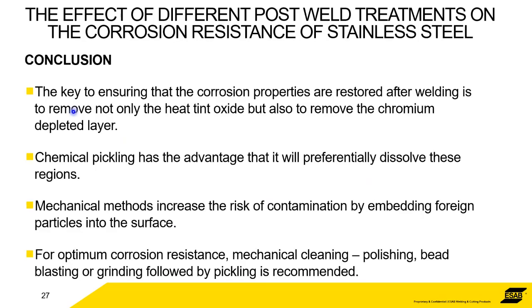So in conclusion, it's key that it's not just the heat tint that's removed. You have to remove the chrome depleted layer. That's a little bit surprising and a little bit more difficult, maybe. Chemical pickling is the best because it preferentially grabs hold of the chrome depleted layer, and it grabs hold of the chrome oxides. So it will dissolve those regions. It's very controllable. It's relatively cheap. So it's absolutely what we would recommend.